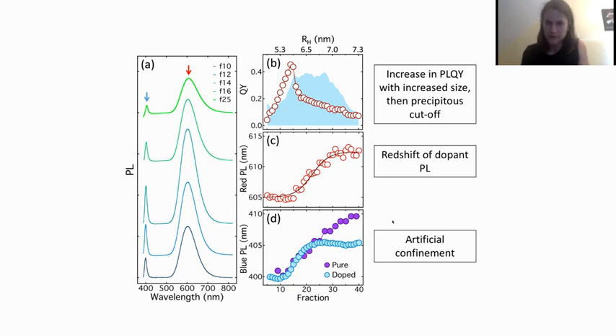Then we also observed a curious effect where, for the doped crystals, their bulk band gap is at 410 nanometers. So you'd expect that once you get to a large enough size, this blue line should cut off at 410. But we noticed that it's saturated below its bulk level. To see if that was real, or if it was due to the dopants, or if the blue emitters showed some peculiar property, we made a pure sample, so undoped crystals, and size separated them, and that's this purple line. You can see that it does saturate to where you would expect for the bulk band gap.